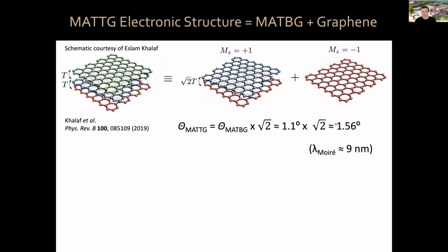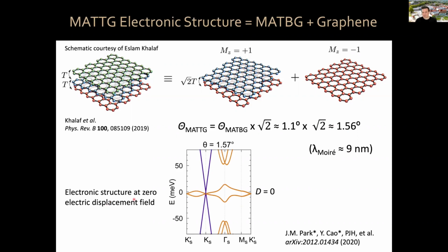So that also means that the Moire wavelength, which for magic angle twisted bilayer graphene is around 13 nanometers, for the trilayer case is 9 nanometers. So it's a shorter Moire wavelength, which can have implications for the strength of Coulomb interactions. Now, this is the electronic structure when there is no vertical electric displacement field applied to the structure. As you can see, it's indeed the combination of a set of flat bands, which come from the magic angle twisted bilayer graphene-like part, and then you have the regular massless Dirac electrons from the monolayer part. Now, this is at 0 displacement field.